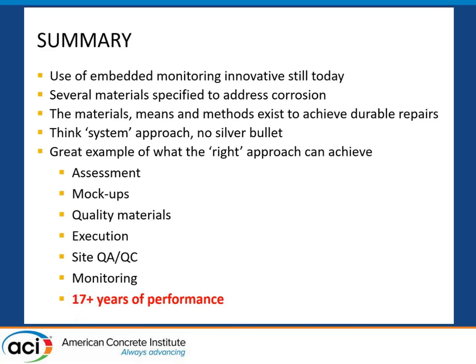I think this is a great testimony of when you get a good team together, they work collaboratively. They're not trying to point fingers. We're trying to arrive at a solid solution and work together. They do an assessment, a mock-up, quality materials, a good experienced contractor. There is QA, QC on site. Then they do monitoring, and all of that gives you 17 plus years of performance. Keep in mind where they were in 2000, at 10,000 spalls. It increased 25% in those 5 years. And here we are 17 years later, and there's virtually no spalling on this project.